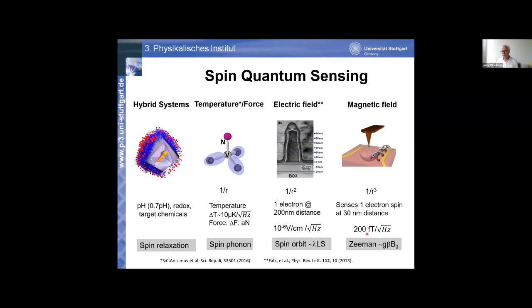As we will see, the record values for sensitivities are on the order of a few hundred femtotesla per square root of hertz. If you compare this with other magnetometers like atom vapor magnetometers, for example, then this is easily like 2 orders of magnitude less sensitive than these magnetometers are. Also, if you take a SQUID, superconducting quantum interference device, sensitivities easily reach a femtotesla, whereas here we are pretty much limited to 200 femtotesla. So that's a limitation. On the other hand, these sensors are technically very easy to do and can be very compact, as you will see. And this is where the profit comes from.